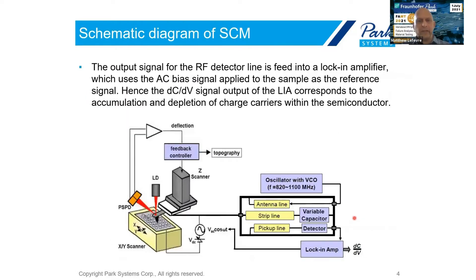Just to step back a little bit, this is our tip-sample interaction. Over here on the right is our sensor. We're going to take the output from the sensor and put it into a lock-in amplifier. The reference for that lock-in amplifier is going to be the AC signal that we're applying to the sample and tip. With that, we get our output signal. We can look at both amplitude and phase from the lock-in amplifier, so we're looking at the change of capacitance with change of voltage.